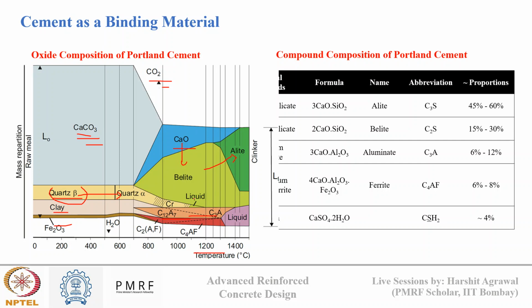So this is also one of the differences between hydraulic lime and Portland cement. In hydraulic lime, limestone is heated only up to 700 to 800 degrees Celsius. That's why the lime there is mainly composed of belite. However, in cement, due to high temperature exposure, both the alite phase and belite phase are present. So that is also one of the key differences between old cement and new cement in terms of the manufacturing process.